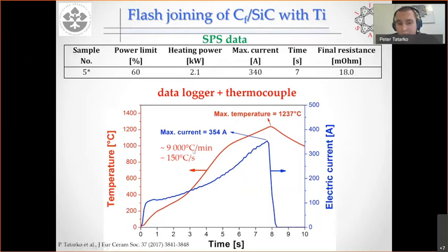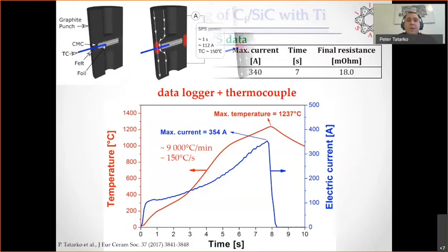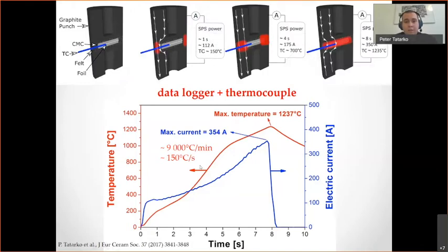You can see an extremely high heating rate. It's 9,000 degrees C per minute, or if you want, it's 150 degrees C per second. So it's an extremely fast process, and that's why the diffusion of these two elements was delayed or hindered. Okay, I can skip that.